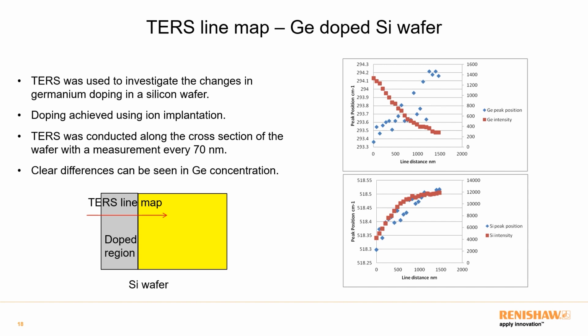Here we can see a gradual decrease in the germanium intensity as we go towards the bulk of the wafer, and we can also see how the germanium peak position changes, which is an indicator of the relative strain in the germanium structures in this wafer. The same can be done with the silicon, so we can again see how the silicon changes as we have more germanium-rich regions and how that impacts its mechanical properties.